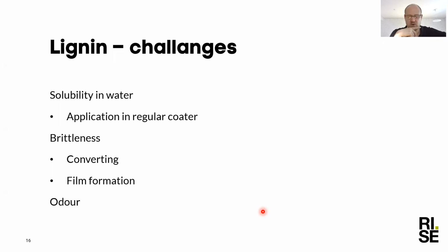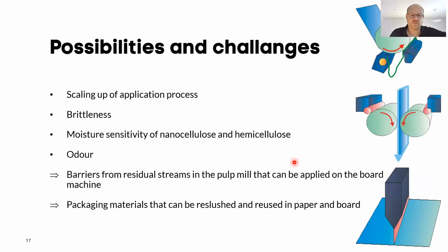So finding a good plasticizer is one thing, and then there's the odor. I have a former colleague who says it's not a problem to remove the odor, so I just have to take his word for that one at the moment. Once we have solved these challenges, we actually have the possibility of scaling up. And scaling up, I think that's something that we need to do here. Scaling up the results of KTH would definitely be very interesting to try. The brittleness of these materials, of course, the moisture sensitivity of nanocellulose and hemicellulose, but there are some ways around it, and the odor of lignin, as I mentioned.